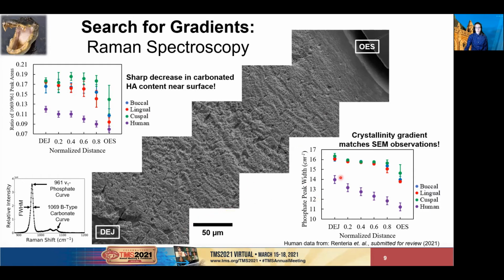We see that the highest degree of crystallinity in alligator enamel is at the surface of the tooth, while it decreases pretty sharply and significantly moving towards the dentin enamel junction, which is exactly what we expected looking at the microstructure. The frequency and size of intercolumnar gaps decreases the closer you get to the outer surface. Interestingly, the narrowest phosphate peak width measured in alligator enamel is still wider than the broadest measure from humans. One possible explanation for this is a higher protein content, but a thorough quantification of the composition needs to be conducted before we can make any solid conclusions.